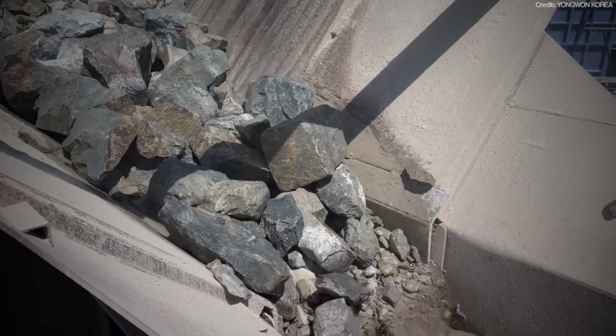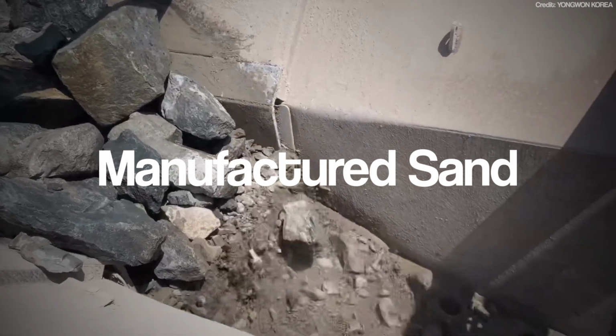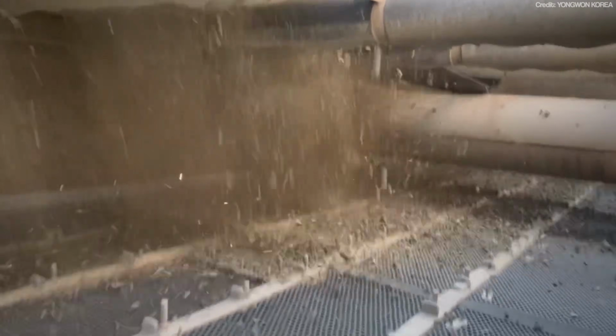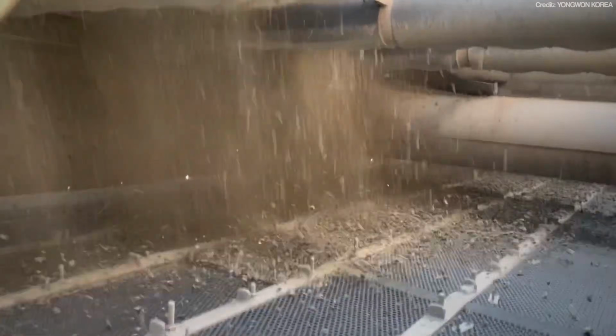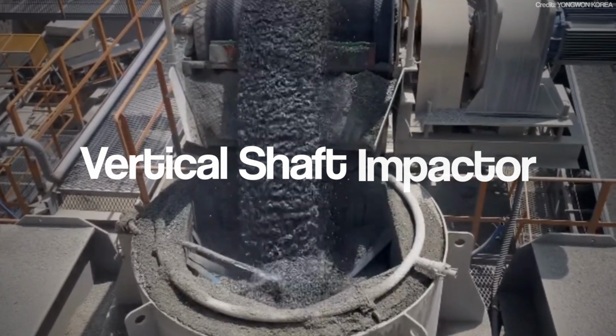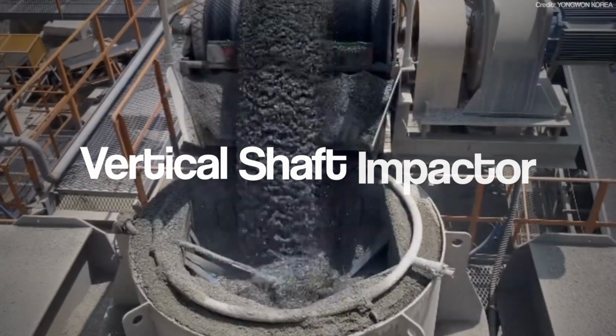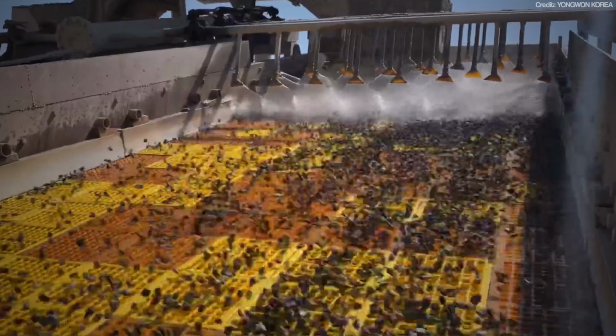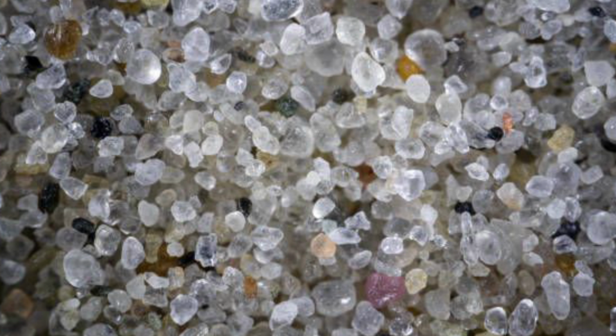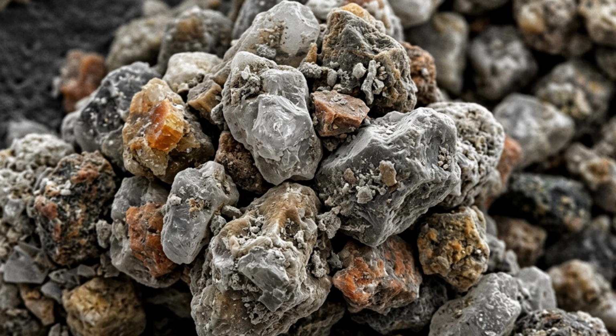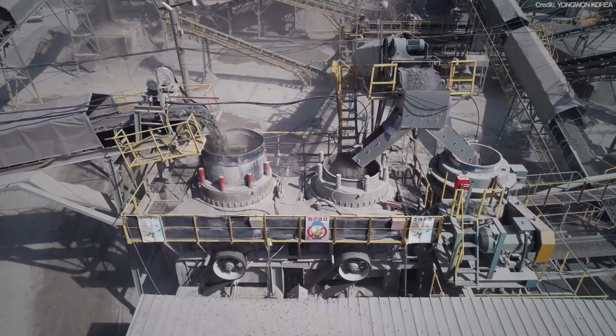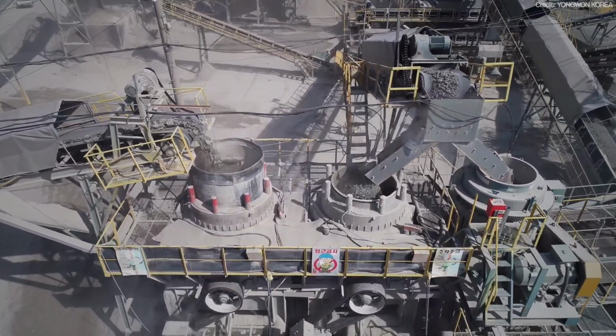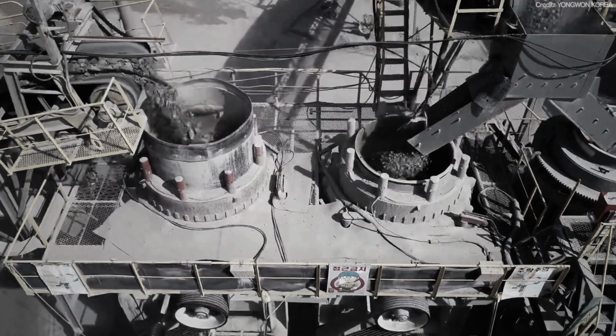The most immediate solution is manufactured sand. Instead of waiting for a river to grind rocks over 10,000 years, we do it in 10 seconds. Using a vertical shaft impactor, we throw hard rocks like granite against a rock shelf at high speeds. This creates a cubical grain that mimics the interlocking properties of river sand. It's more energy intensive, but it's 100% sustainable as long as we have rock.